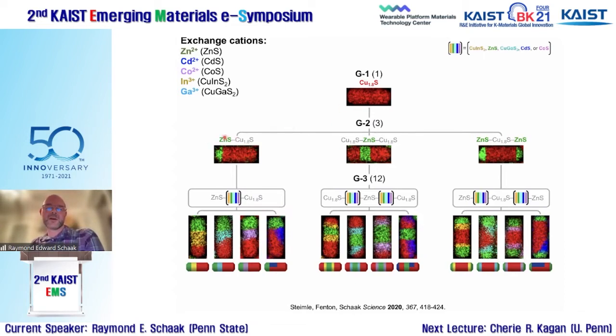So in this first exchange step, we use zinc 2+. We have five total cations. We'll eliminate zinc 2+ from the next set, and we've got four other cations. So we'll take this zinc sulfide, copper sulfide tipped rod, and we'll exchange it with each of these four remaining cations that will produce a segment at this pre-existing interface. So we'll get copper indium sulfide here, copper gallium sulfide here, cobalt sulfide here, cadmium sulfide here. Same thing here, except because there's a central band, there's two interfaces. So the subsequent exchange reactions kind of step outward. Here there's two interfaces, but the subsequent exchanges step inward. Long story short, from these three nanorods with zinc sulfide, we can make 12 derivatives.